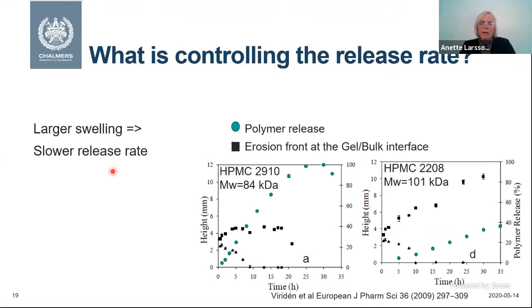And this also influences, of course, the swelling. So here is an example where we have the release curve, so how much of the polymer is released. Here we can say 40% is released, here 100% is released. And the erosion front is the front where we have the bulk gel interface. You can see in this case where we have slow release, we got a large degree of swelling, which indicates that a lot of water was needed to penetrate into the gel before we reached the point where we reached the critical concentration. So that strengthened our theory. That was an indication that the h, the thickness of the diffusion pathway, has a very clear impact on the drug release rates.